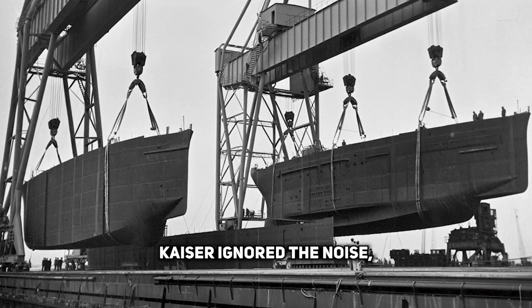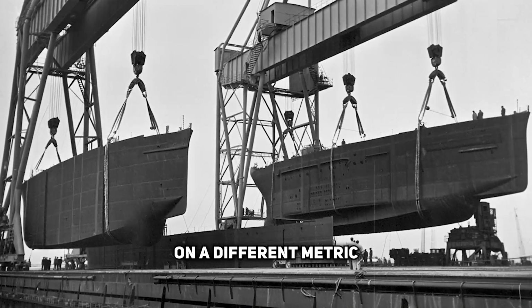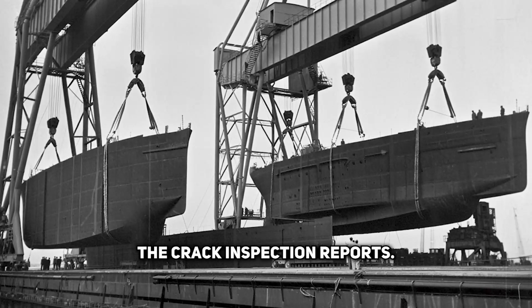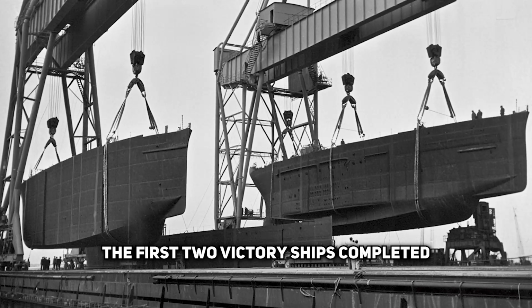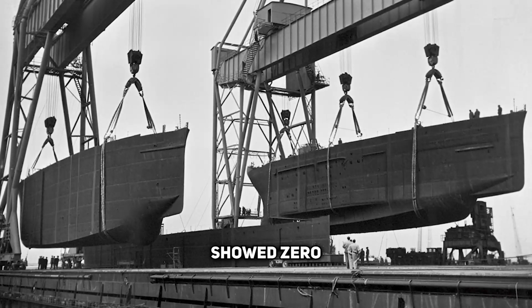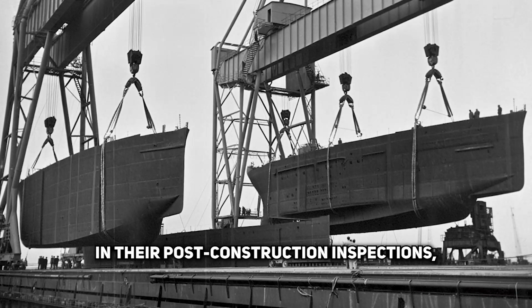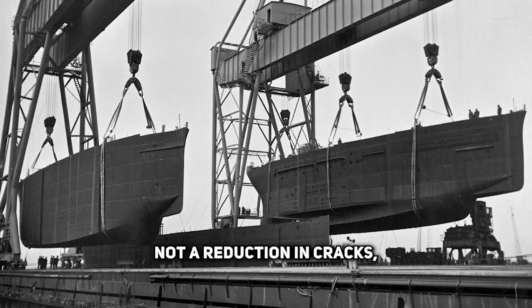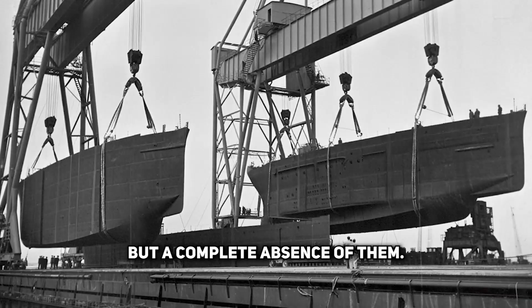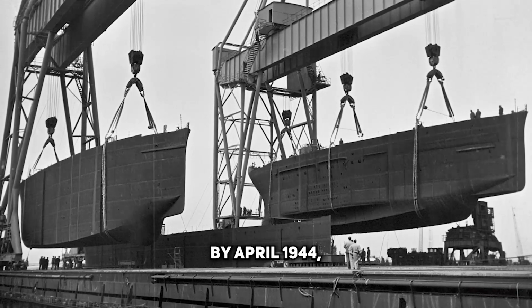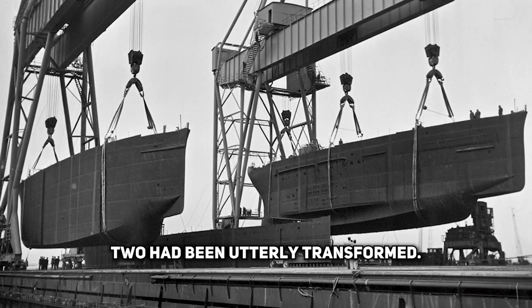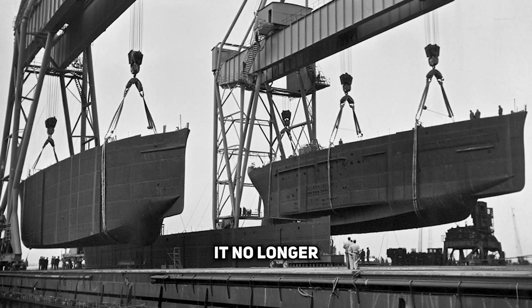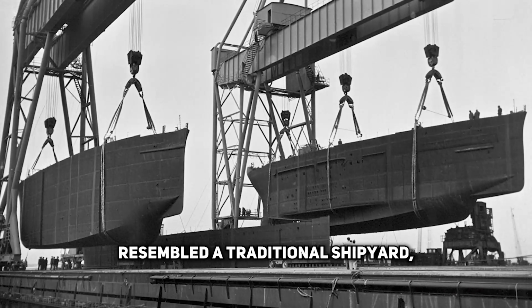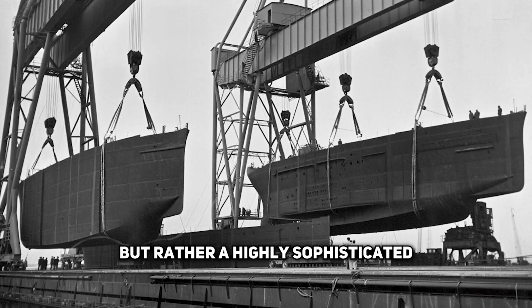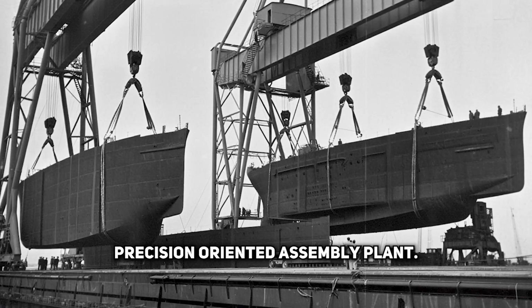Kaiser ignored the noise, focusing instead on a different metric, the crack inspection reports. The first 2 Victory ships completed showed 0 stress cracks in their post-construction inspections, not a reduction in cracks, but a complete absence of them. By April 1944, Richmond Yard 2 had been utterly transformed. It no longer resembled a traditional shipyard, but rather a highly sophisticated, precision-oriented assembly plant.